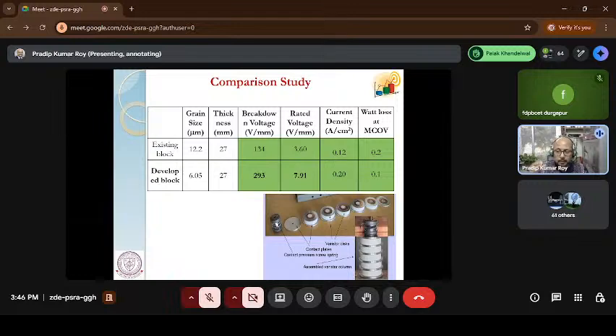Earlier, if you remember, to make a 400 kV surge arrestor, I was using 133 blocks. Now my rating is 7.9, almost 8. So if I make a 400 kV arrestor, I need only 50 blocks. Today people are talking about 1400 kV surge arrestors, and if I make it around 8, you can imagine that I can reduce the total surge arrestor height.